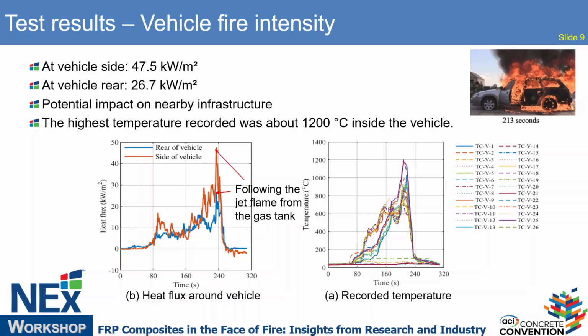There's a steel cable around the vehicle, and such a high heat flux will lead to degradation of the steel strength of the cable, which may endanger the bridge. And we also recorded the temperature in the vehicle, and the maximum temperature we measured inside the vehicle is almost 1,200 degrees Celsius, which is measured inside the vehicle compartment fire.